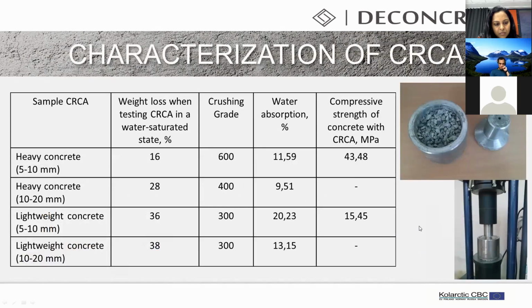And also, we started to think about coarse recycled aggregates, and we tested them using our press, and we measured the strength of crushed stone. In Russia, it is characterized by a grade determined by the crushed stone crushing during compression in the cylinder, grinding grains, depending on the weight lost when testing crushed stone in a water saturated state.